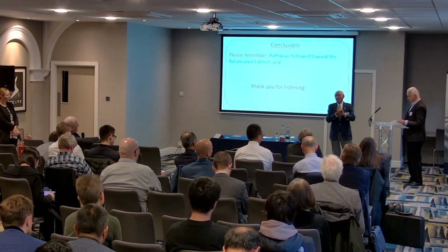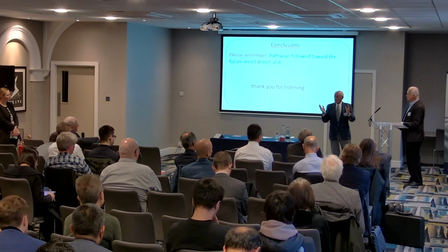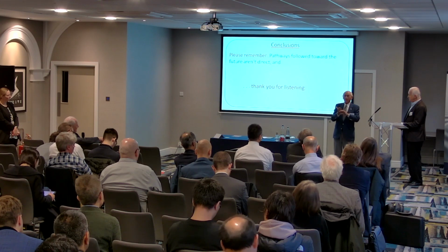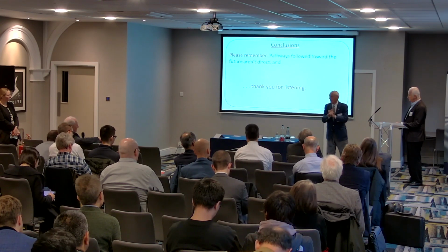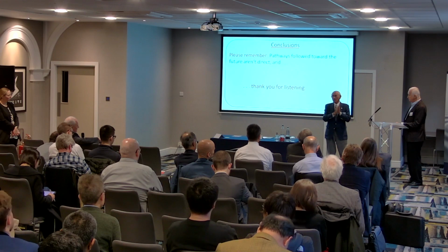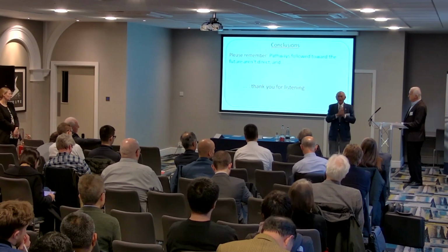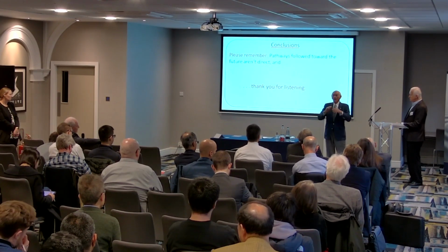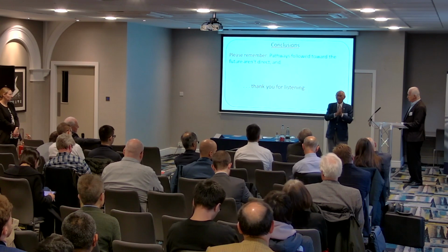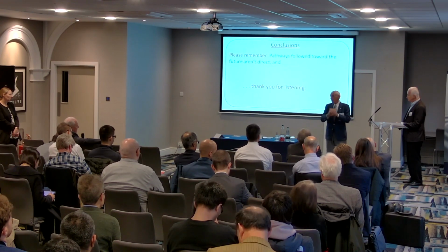My question is, can you think of casting processes in the future where, since these are deterministic currents, you can calculate them, therefore you can interact with them? You might be able to apply magnetic fields. Now the Chinese are doing that. They're putting fields on up to 12, 13 Tesla. And they're finding out that the surface energy, and these are in metals, between the solid and the liquid is going up with the static magnetic fields. That means all these effects go up proportionately. In addition to magnetic fields, pressure should affect them as well. So you can interact with these things deterministically.